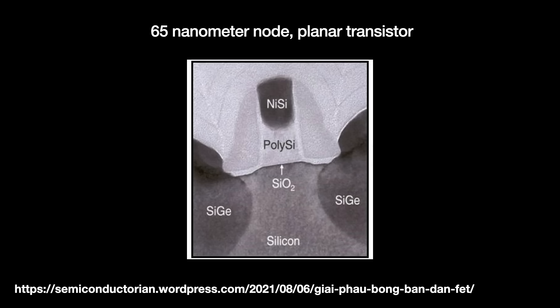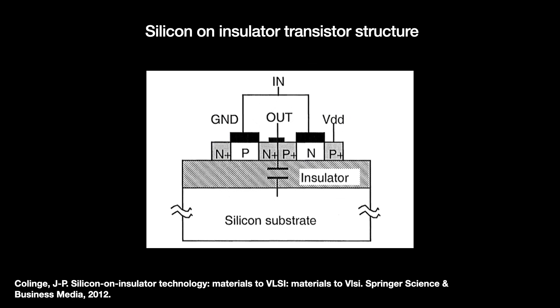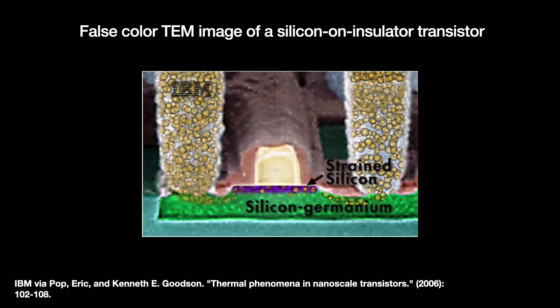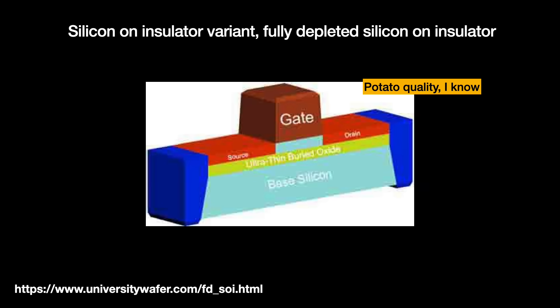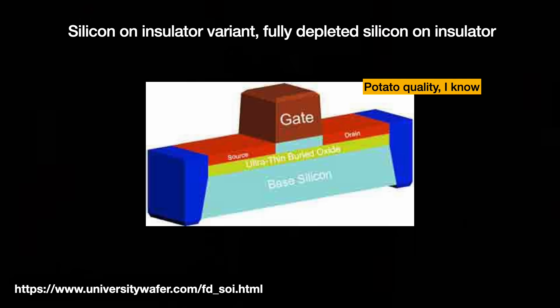The device's dimensions got so small that we could not prevent charge carriers from crossing over from the source to the drain. A new modification introduced to address this issue was the silicon-on-insulator, where we slide a layer of insulating material like oxide under a planar transistor, separating it from the silicon substrate. The insulator lets the transistor switch faster and helps prevent charge carriers from burrowing under the channel. But insulator materials like these oxides tend to be poor thermal conductors, essentially keeping the heat from dissipating into the silicon substrate — kind of like why they put insulation into houses.